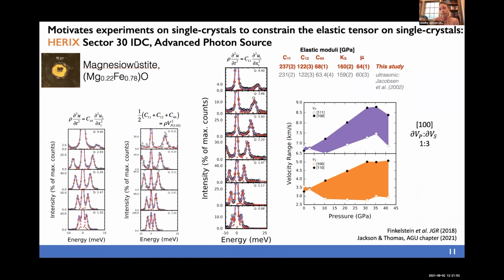So this has also motivated the study of single crystals of magnesiowüstite. This is enabled by the high energy resolution inelastic X-ray scattering beamline at Sector 30 ID-C. We're able to conduct very beautiful measurements to constrain the dispersion relation of the acoustic phonons, both P and S waves, of this magnesiowüstite single crystal. This is led by, at the time, postdoc Greg Finkelstein, and compared with ultrasonic results, found very good agreement.